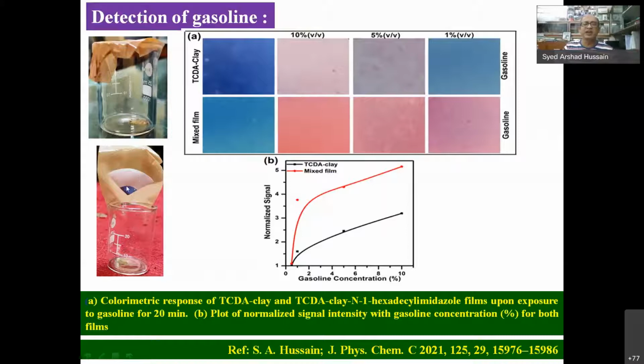Then we put the film here, and you can see based on different volume ratio, the color changes. For both TCDA clay as well as mixed films, you can see. And then we analyze the normalized signal intensity, and you can see the plot. It's almost linear with concentrations. And of course, beyond 5 for TCDA clay it is linear. So one can have an idea about these things.